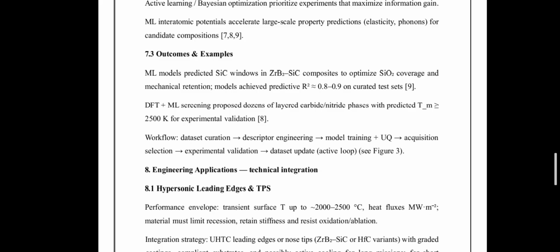For layered carbides and nitrides, combined DFT plus ML screening proposed dozens of candidate phases with predicted Tm above 2500 K, ready for experimental validation. These examples demonstrate that ML accelerates discovery, identifies composition-property relationships, and helps navigate the vast UHT design space much faster than trial and error experiments.